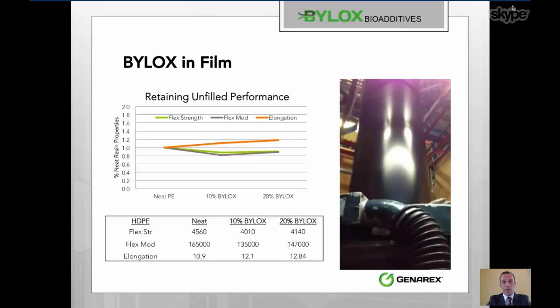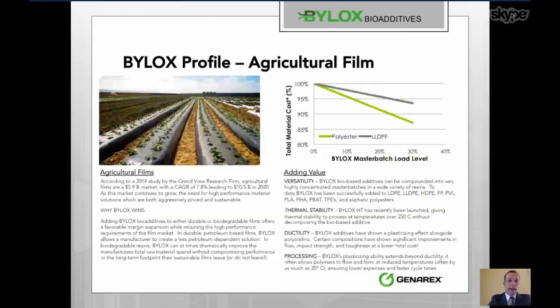We're very excited with what we can do in both polyolefin films as well as more sustainable plastic films, such as agricultural films. So in the agricultural film space, we think that we add value to both petroleum-based products or the biodegradable type products, as well as the polyolefin products. Obviously, the more of a low-cost filler or additive that you're able to incorporate, the more of a price break you get. The more expensive the base resin is, the more significant that savings is. But we've found significantly and consistently that our product has worked both to fill and retain performance, as well as, in some cases, improve oxygen barrier characteristics.